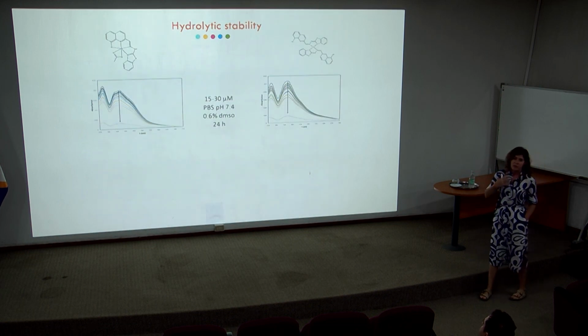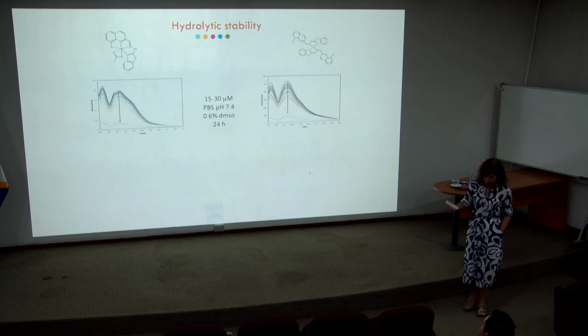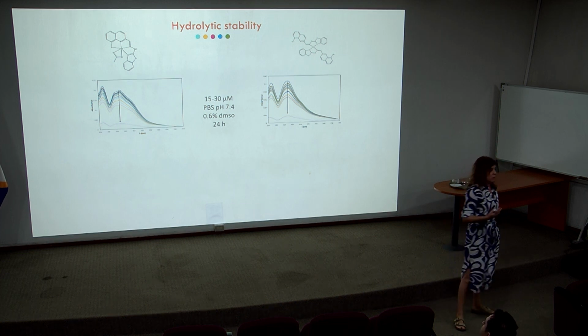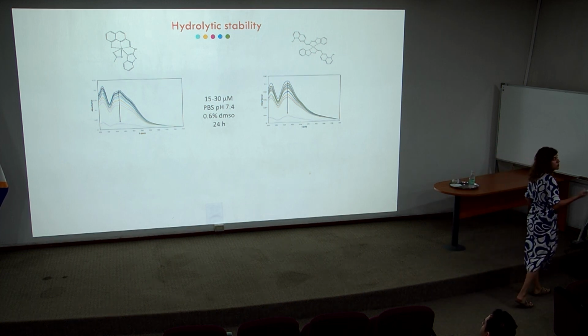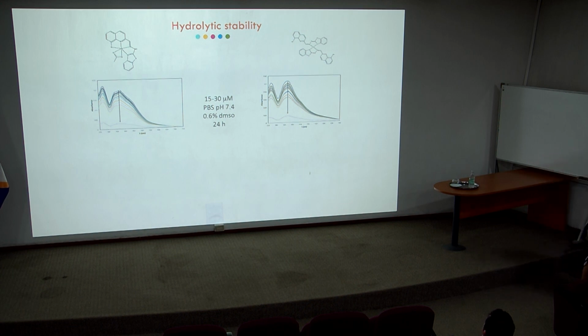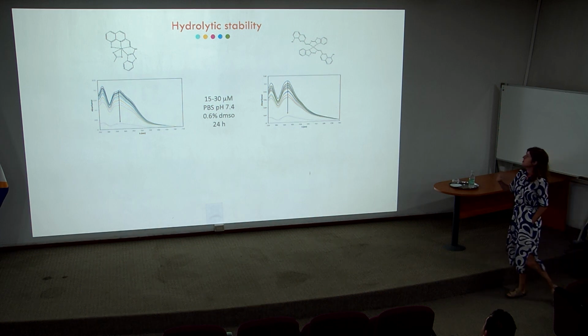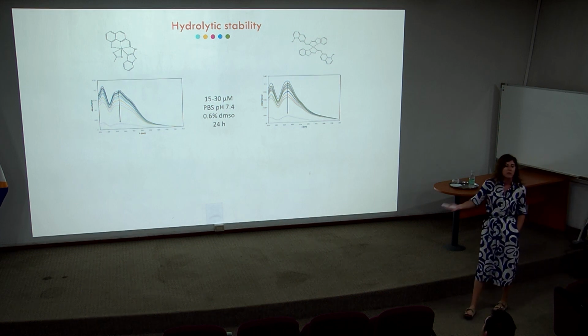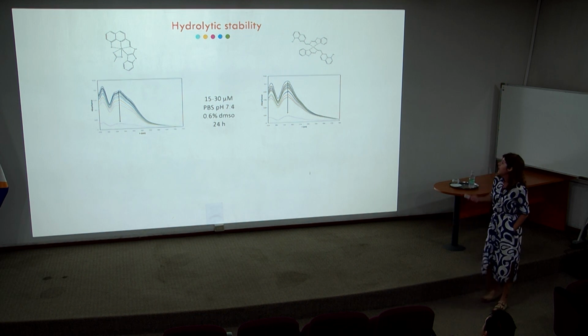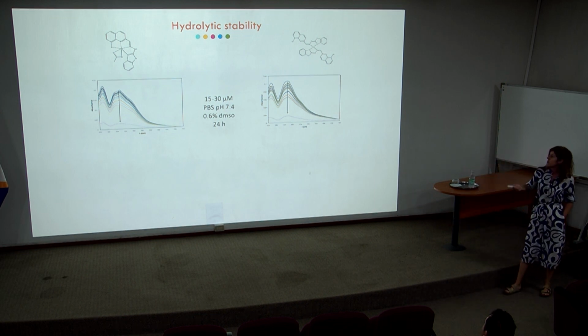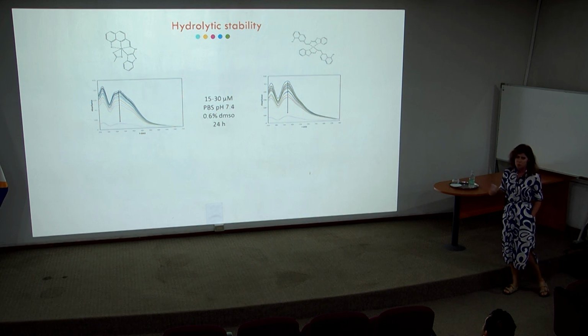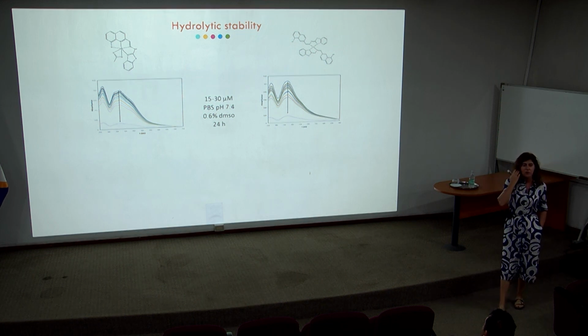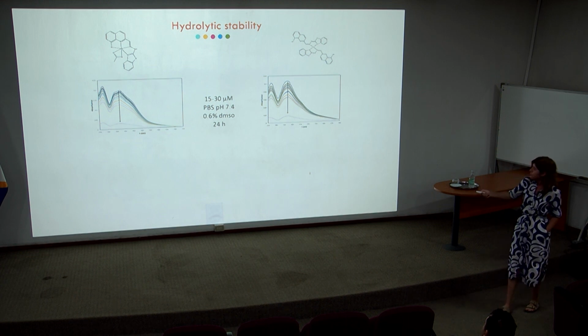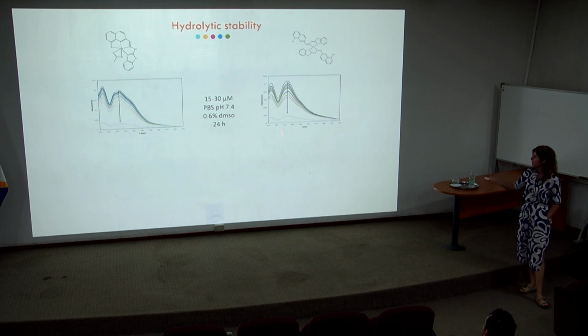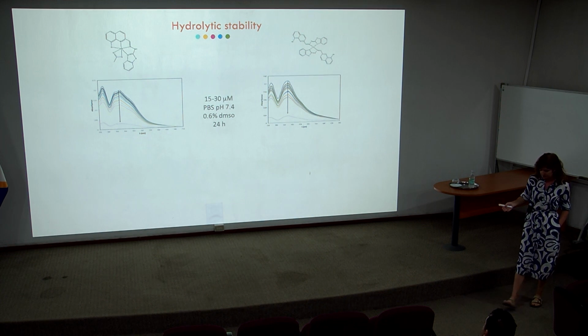One thing that we always need to evaluate is what happens to the compounds when we put them in aqueous solution at physiological pH. Because, as I've said, the ligand is quite lipophilic. The complexes are also lipophilic, although we did not measure it experimentally. But what we typically observe is that at concentrations which are relevant for the biological studies, in the low micromolar range, we can see that within 24 hours, the compounds precipitate.